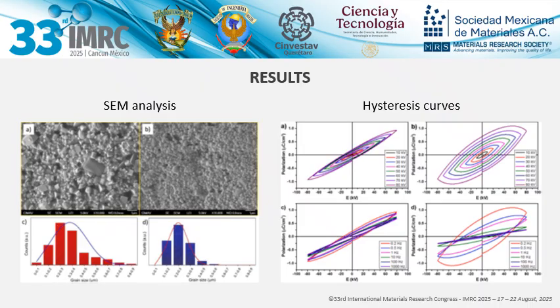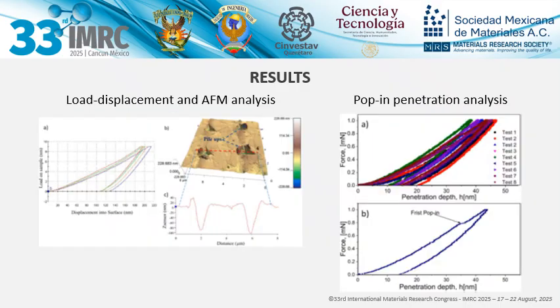Ferroelectric properties. The hysteresis loops showed a clear improvement in ferroelectric behavior. The remnant polarization increased from 0.201 microcoulombs per square centimeter to 0.695 microcoulombs per square centimeter with aluminum doping. This indicates greater mobility of ferroelectric domains and fewer non-ferroelectric phases. The coercive field also increased, suggesting improved polarization stability.